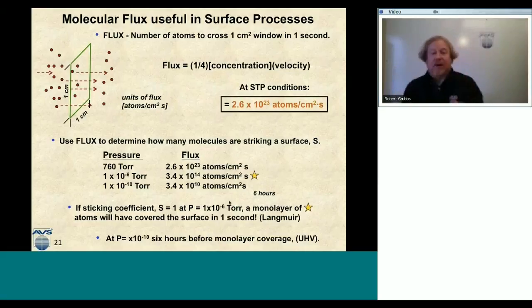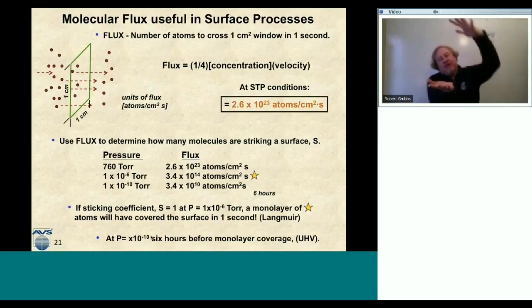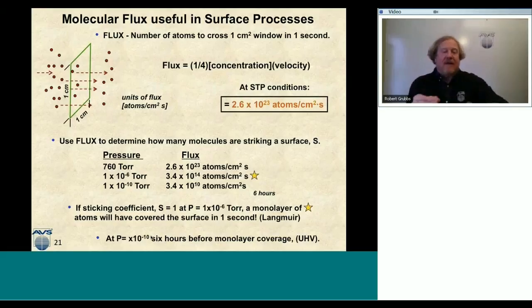If we go down in pressure, to 1 times 10 to the minus 10 torr, we get a very small flux, like 10 to the 10 atoms per centimeter squared per second. At a pressure of 1 times 10 to the minus 10 torr, it takes 6 hours before a monolayer will cover a surface if the sticking coefficient is 1. That's why experiments are done in ultra-high vacuum. If I have ultra-high vacuum and cleave the surface, I have 6 hours before I can do a delicate experiment on that unadulterated surface before a monolayer of material, primarily carbon, contaminates that surface and doesn't let me collect data on it. So at 10 to the minus 10 torr, you have about 6 hours before 1 centimeter squared is covered with material.